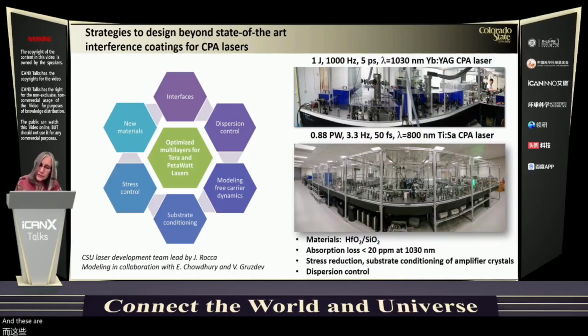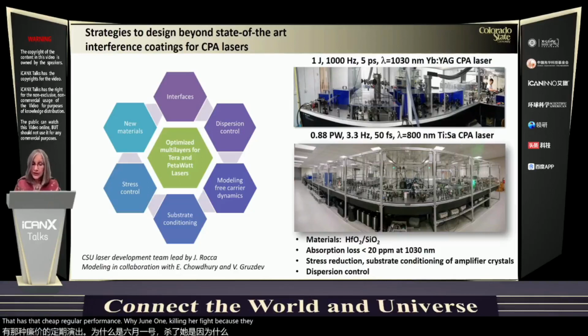And these are one ytterbium YAG chirped pulse amplification laser that has achieved record performance, 1 joule, 1 kilohertz, 5 picosecond pulse duration, and a petawatt class laser based on titanium sapphire. And so here the materials that we use for coatings are hafnium dioxide and silicon dioxide. And what we are looking at is reducing stress. We are also developing strategies to condition substrates. We are looking at the role of interfaces, and we are also looking at new materials.